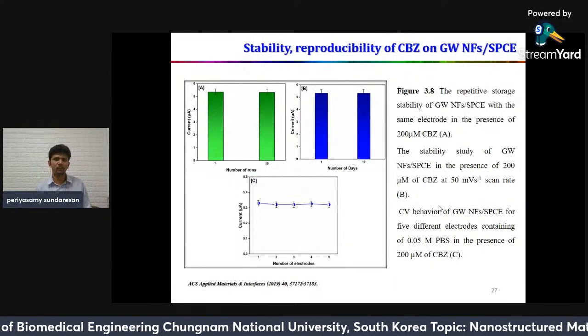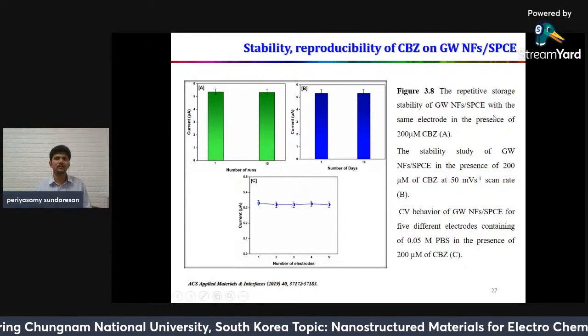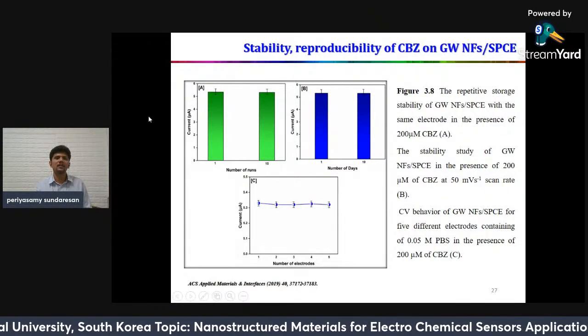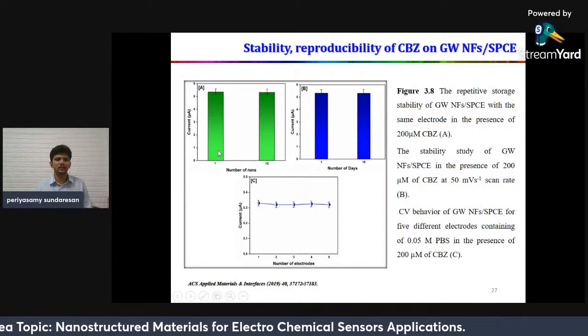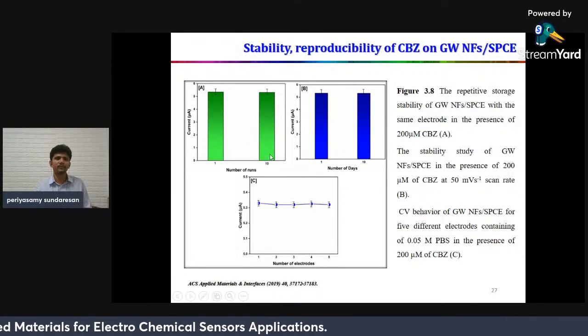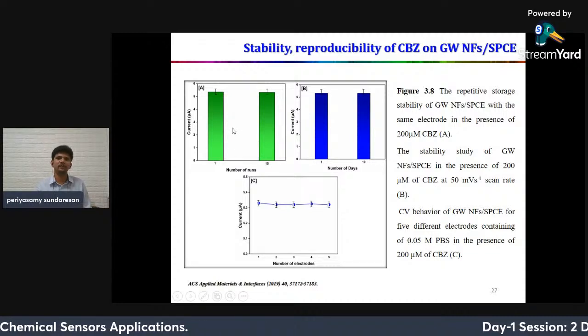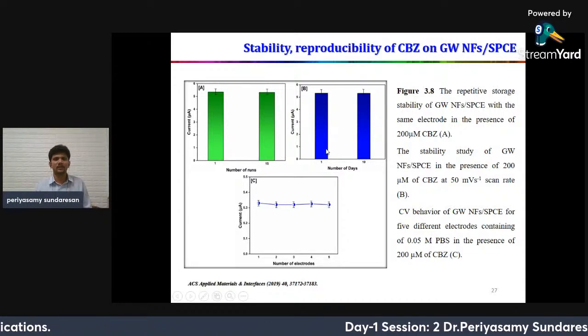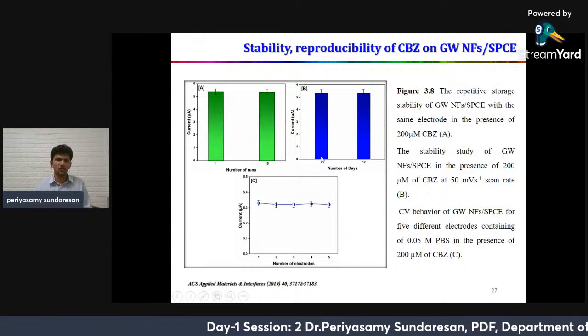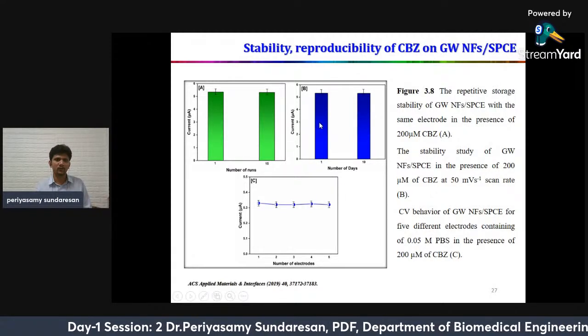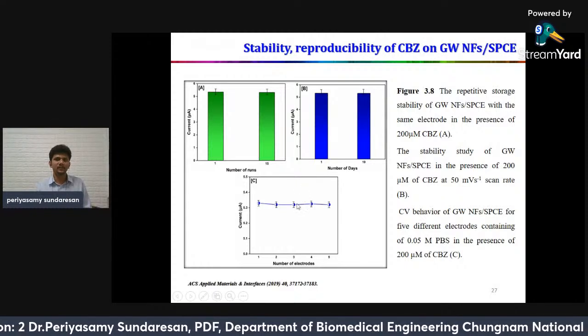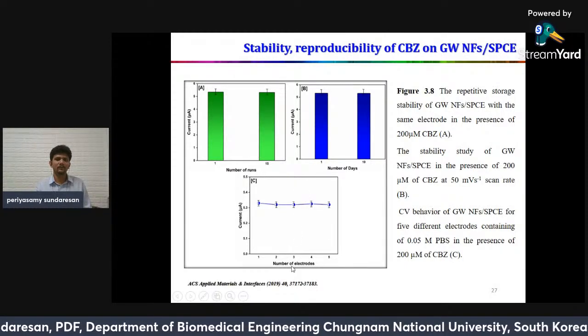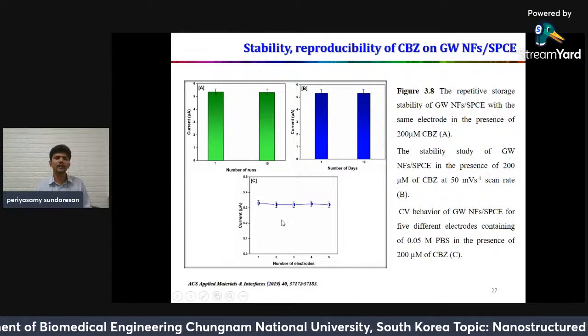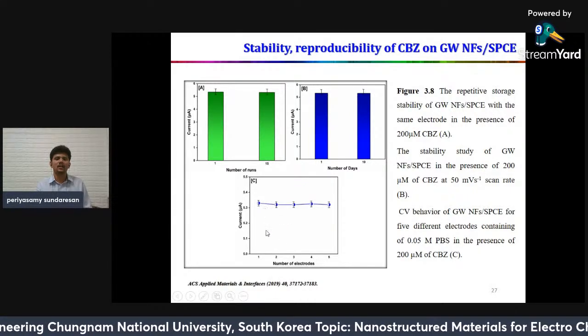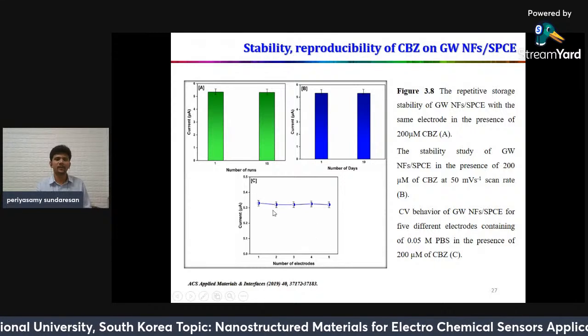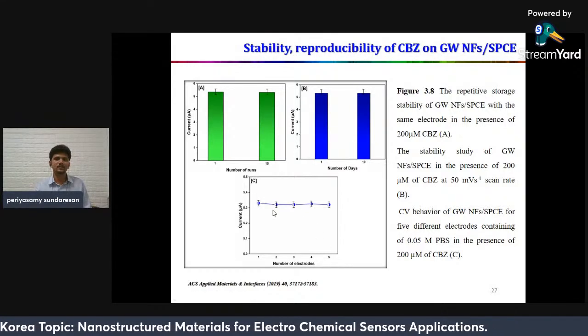This is a stability and reproducibility study of the carbendazim analyte on gadolinium tungstate nanoflakes. If I run it many times, 1 to 15 times, I get the same current response for the carbendazim analyte. If I prepare the electrode over 1 to 10 days, I get the same current response for the analyte. And this is the repeatability test for the prepared catalyst: 5 different electrodes give the same current response for the carbendazim analyte.